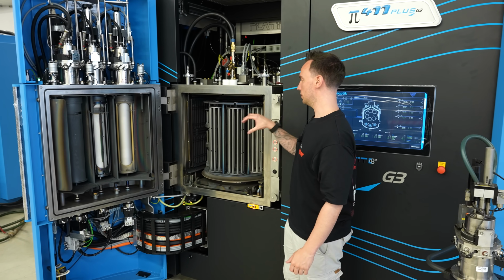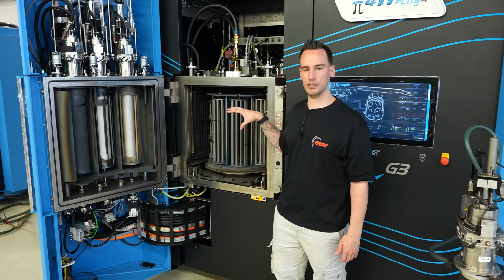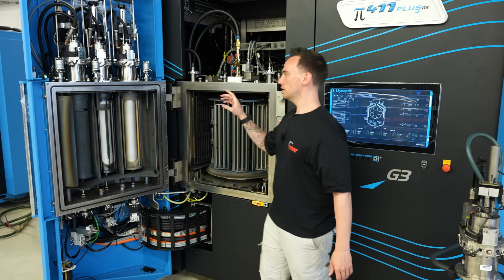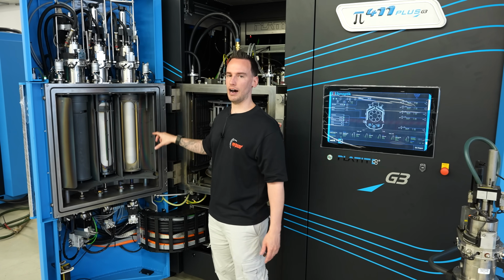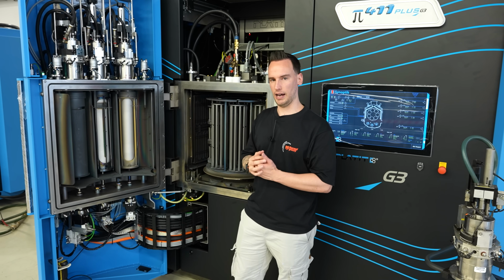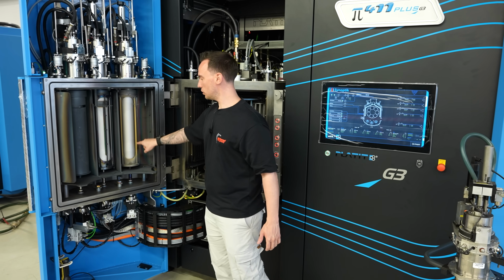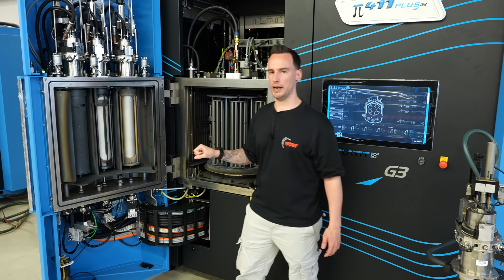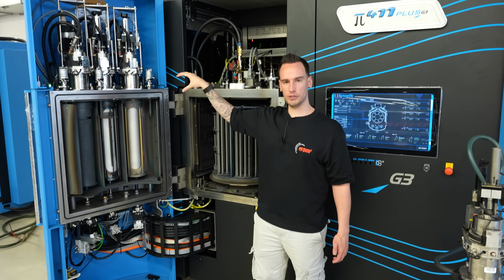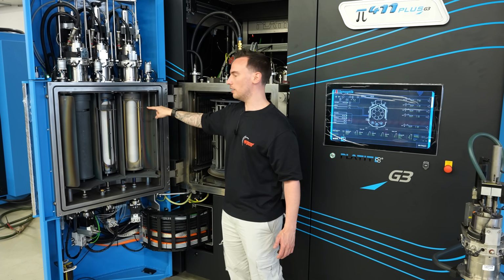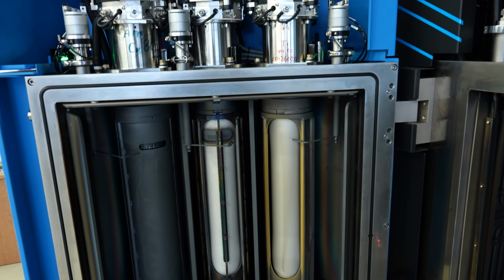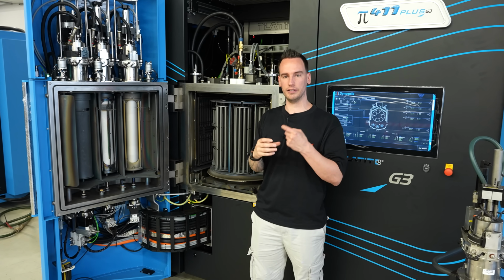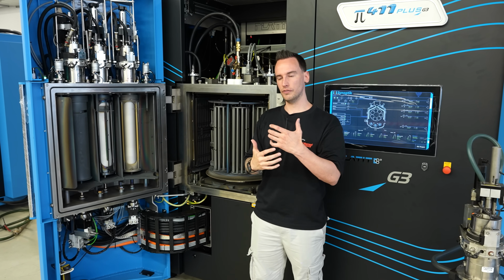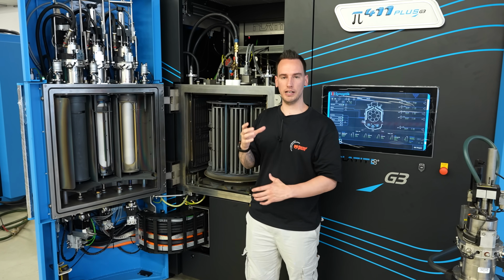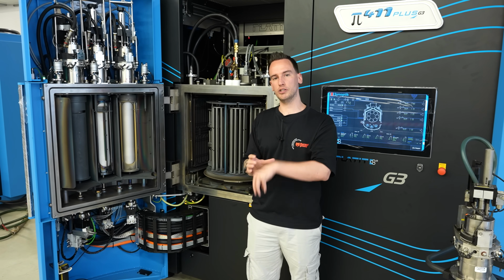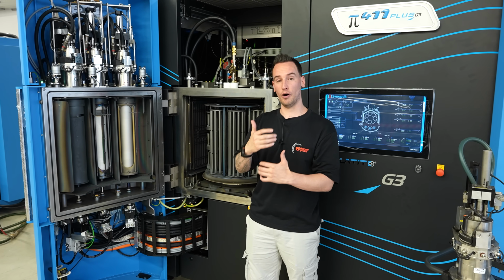And then, once it's closed and everything is prepared, you're heating up the parts to the designated temperature. Then you're using the cathodes, and here you have to create the arc on the surface to release the metal ions. This arc is being generated inside this entire field. It works in a way that there is a big current put onto the cathode itself. Then there is a small arm, a small lever, that is hitting the, in this case, titanium surface and igniting the arc. The arc stays on the surface because the rod, the cathode itself, is not empty, it's hollow, and there's something inside to create a magnetic field that contains this arc on the surface.